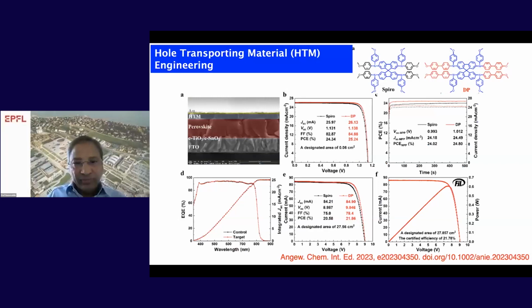The hole transporting material is another interesting category of materials, where the stability of this material is very important. In PIN configuration, people are using nickel oxide or PTAA as the hole transporting material. In the NIP configuration, the majority of the groups are working with spiro-OMeTAD. Spiro-OMeTAD is a non-conducting material which has to be doped with lithium TFSI, tertiary butyl pyridine, and cobalt complexes in order to oxidize.